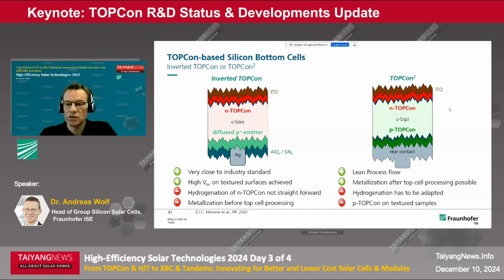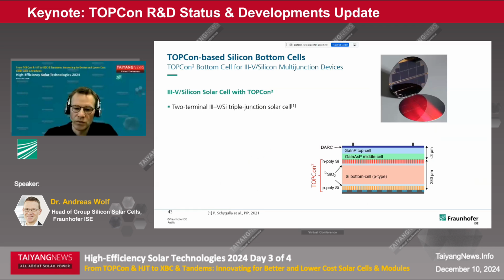One alternative is the TOPCon square structure that we propose. It features full area N-type TOPCon on one side and P-type TOPCon on the other side, which allows a lean process flow. But also here we see some challenges like hydrogenation, and also the quality of P-type TOPCon on textured surfaces still lags behind a little bit compared to N-type TOPCon. We were able to implement the TOPCon square structure in multi-junction devices. In this case, it's a III-V silicon